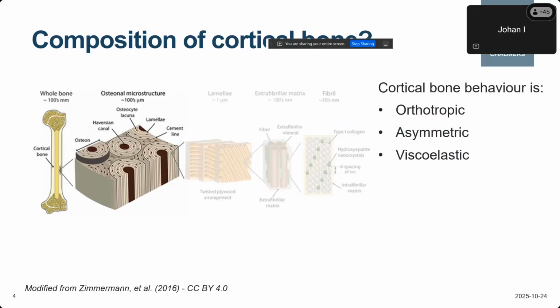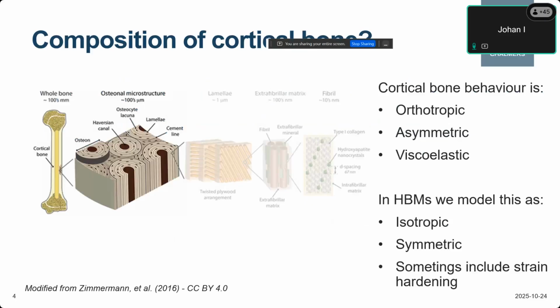It's asymmetric, meaning that it has different properties in tension and compression, and also viscoelastic. So we typically see some kind of strain hardening. For higher loading severities or higher loading speeds, we see higher stresses that can be handled by bone. In human body models, we usually model this as isotropic, symmetric, and sometimes include strain hardening, and we use standard metal plasticity in most cases.